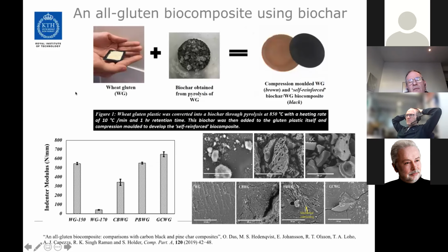We are also looking at other ways of, for example, improving the strength. And here's something that I think is quite interesting. You could produce an in-situ composite by producing a biochar of the same material. So you pyrolyze the gluten, and then the particles you get, the biochar, you can implement into the polymer matrix and improve the mechanical properties if that's needed. So it's an all gluten-based composite.